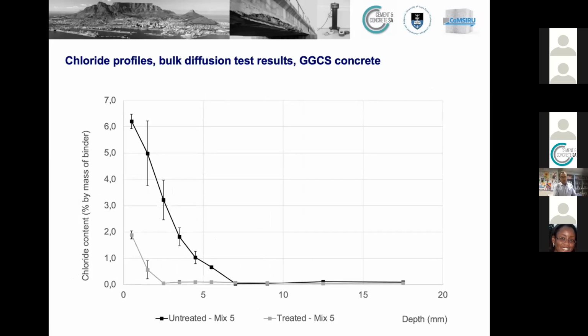So what we could see here is that these hydrophobic coatings are very effective in limiting the ingress of water. And if water is kept out of the concrete, you can also keep out chlorides. If you keep out the chlorides and the water, you will not get reinforcement corrosion. So we then analyzed these curves for diffusion coefficients and chloride surface concentrations and so on, to do some service life modeling.